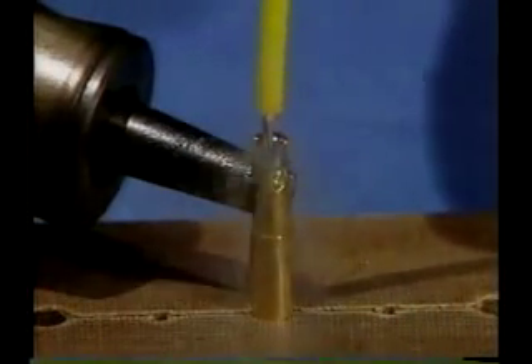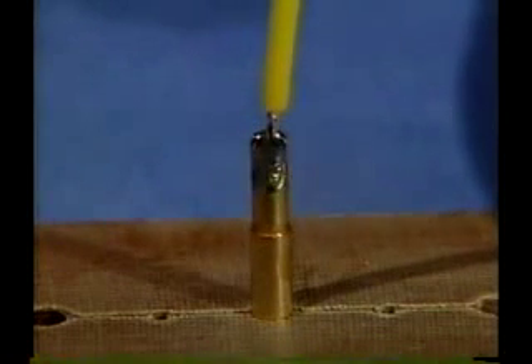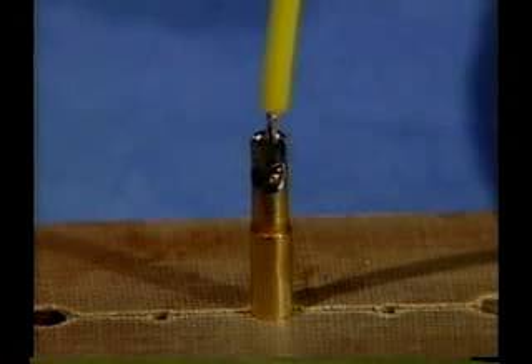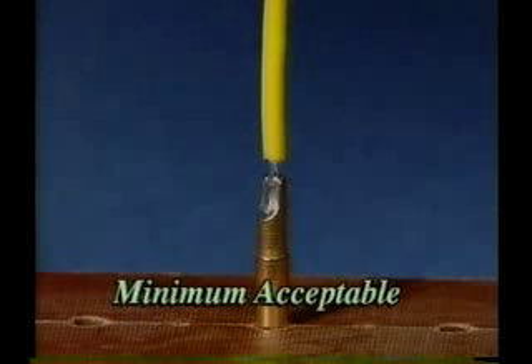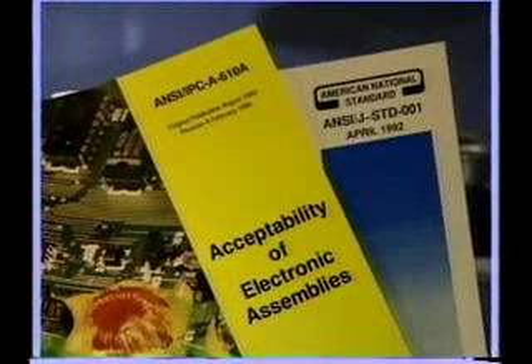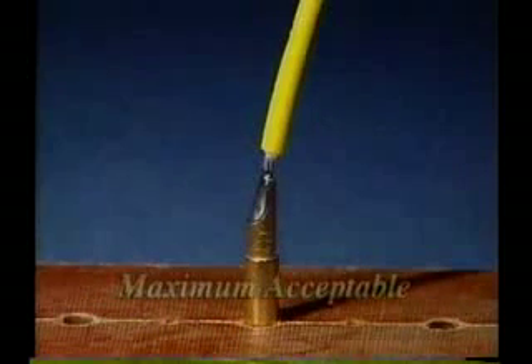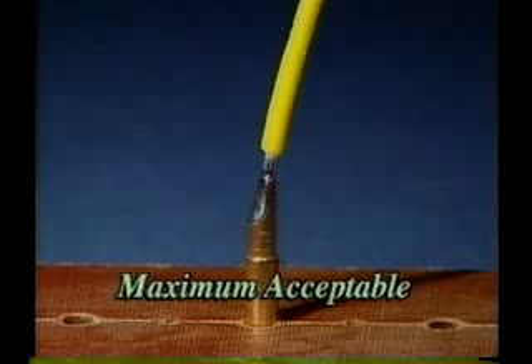Although you should always be aiming at making the best solder joint possible, there is a certain window of acceptability. For example, the minimum solder quantity is dependent on your company's workmanship specification. The maximum acceptable solder joint would reveal fillets that are no longer concave but are beginning to bulge.